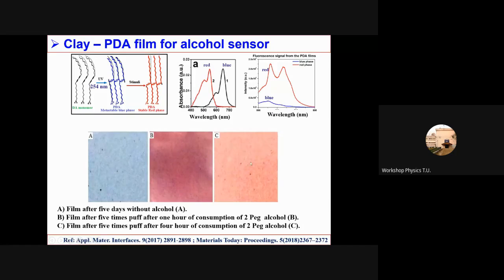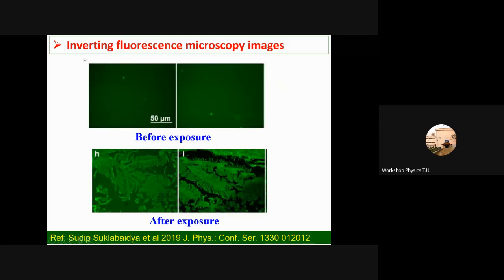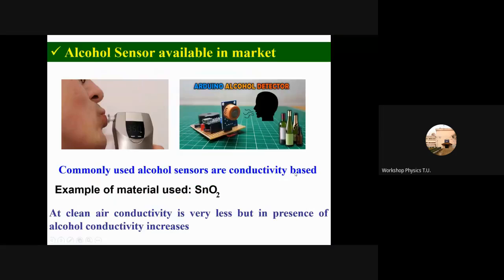Accordingly, the color appeared, and this is again after some time, again exposure, after 4 hours of consumption of alcohol. Still, you see the color change. So just with the naked eye, just observing the color change, you can have an idea about whether a person is drunk or not. Here you can see the corresponding fluorescence microscopy image. This is in blue phase. This is before exposure, the first one, and the second one is after exposure, and you can see the clear polymer structure is visible.